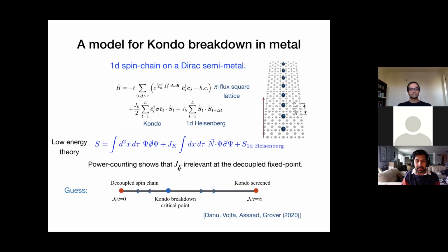So this is a bit like an intermediate thing between a single impurity Kondo and the usual Kondo lattice. The analog of the Kondo impurity here is a 1D CFT. So there's a dimensional mismatch, not of D, but if you like D-1, between the conduction electron and the local moment. And based on RG, you can argue that this decoupled point where J_K is 0 is actually a stable fixed point.